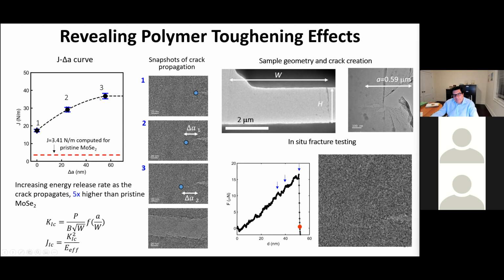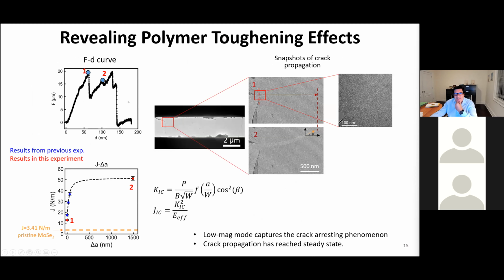And this experiment didn't really reveal in full force the steady state regime. So we did some other experiments with crack lengths of different lengths. And then we completed the data to show that indeed the J delta A curve, in this case for this nanocomposite, extremely thin nanocomposite, has this nice behavior. It's not what we wanted. We wanted to have the pristine material, but it's extremely difficult to remove the polymer, and we try many different approaches. We are still investigating, but we took it as a fact of life and some of the limitations and challenges that remain.